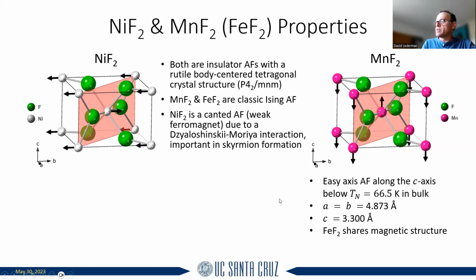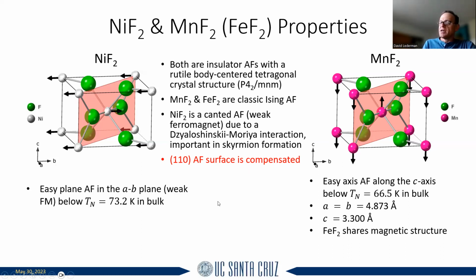so they have some other interesting properties that are relevant to skyrmions. Maybe you've heard talks about this, but I'm not going to talk about that today. But here's the important thing. A lot of the samples that I'm going to show you were synthesized, grown using MBE, with the surface of the film being the 110 surface. And that means that this is a compensated surface, right? This is shown here in this orange. That's the 110 surface, and you can see that you have both spins present at the surface, right? So this is a compensated surface, all right?